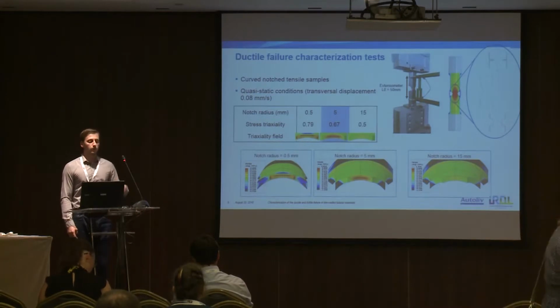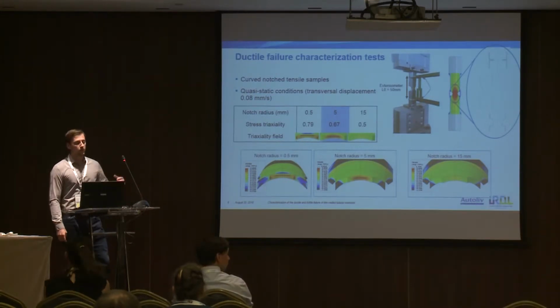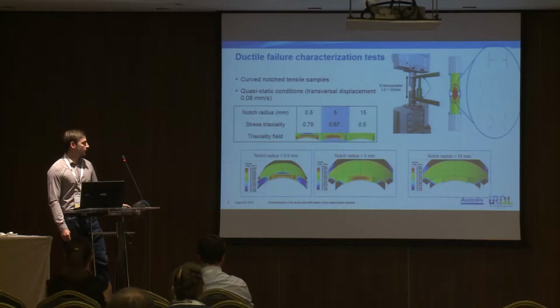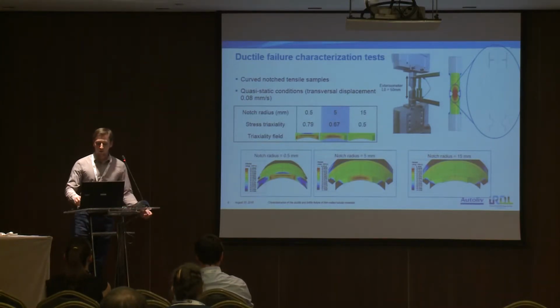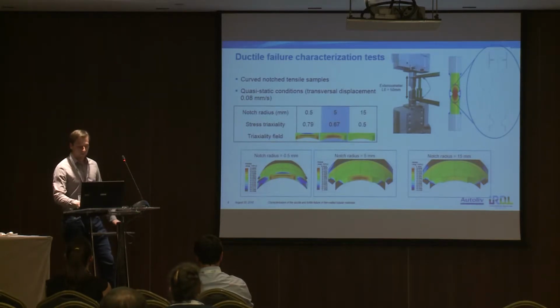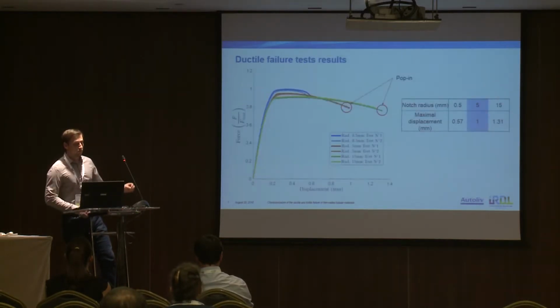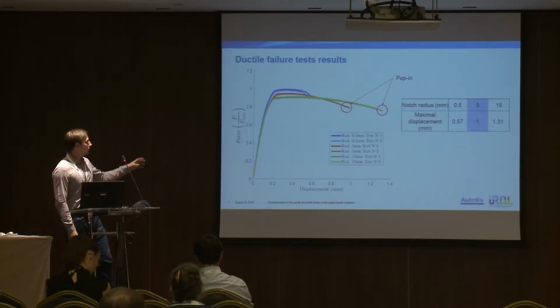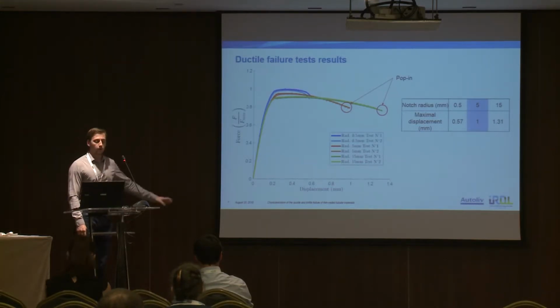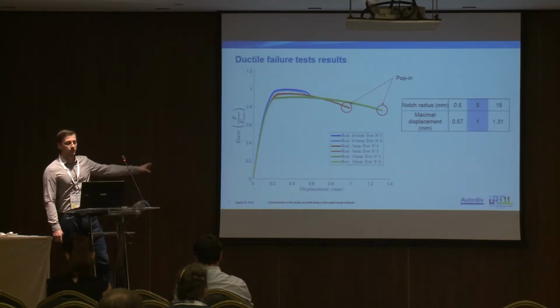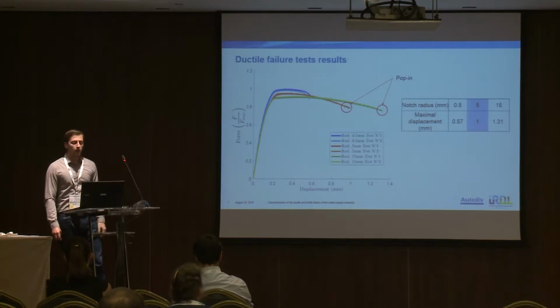And of course, as we are using 3 different radii, there are 3 different maximal stress triaxialities and 3 different stress triaxiality fields. When the design was finished, we proceeded to the test and we got the following results. So here you have the force versus displacement curves for the 3 different notch radii of our sample.